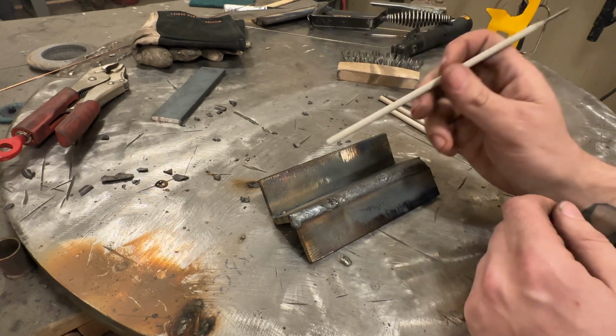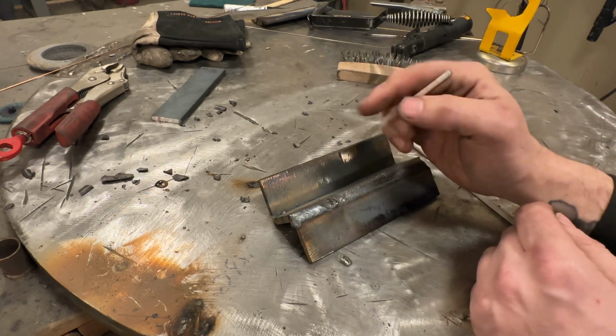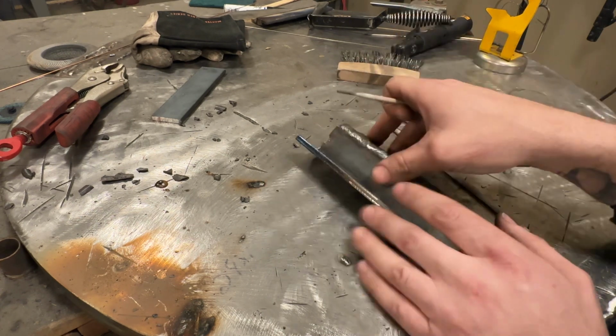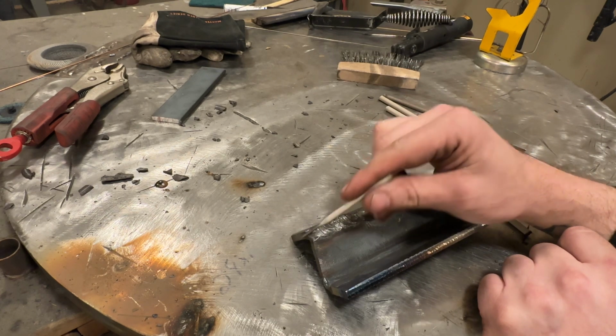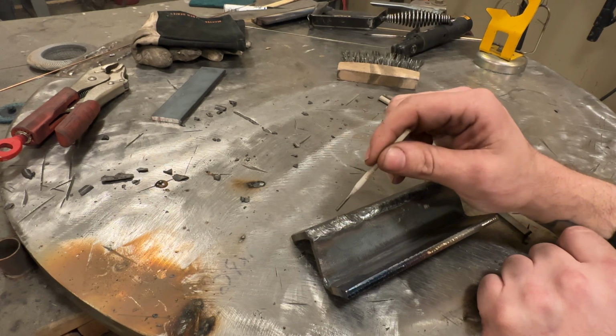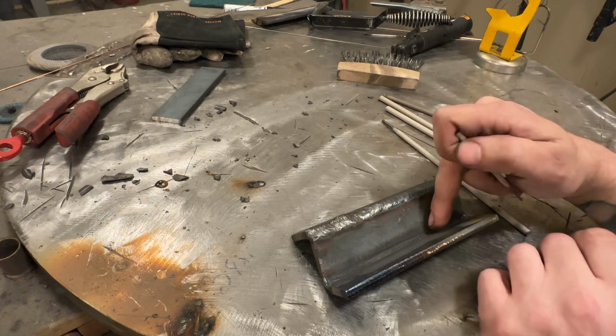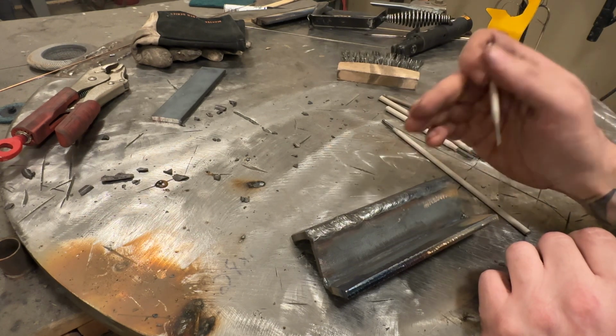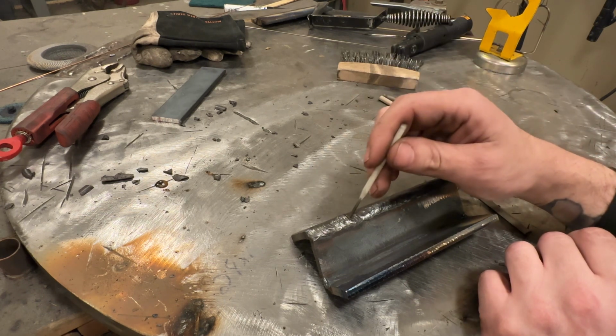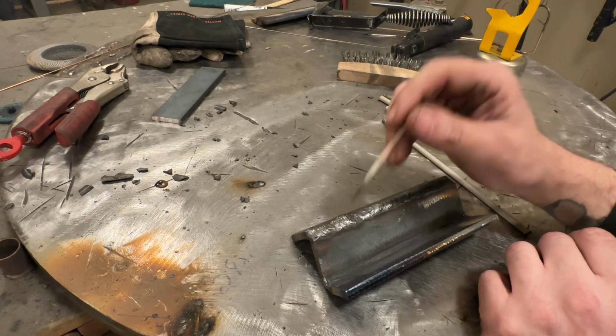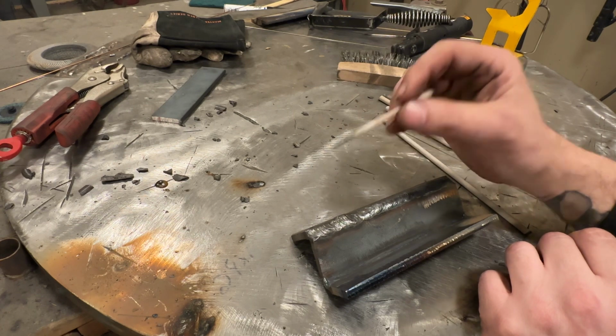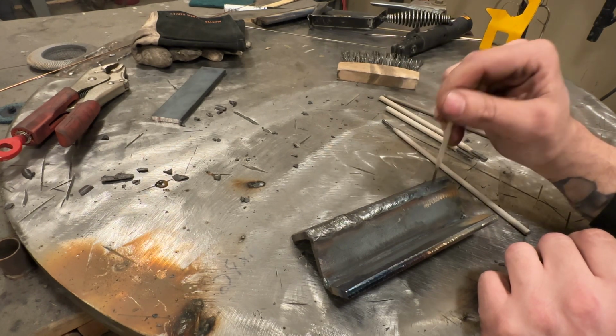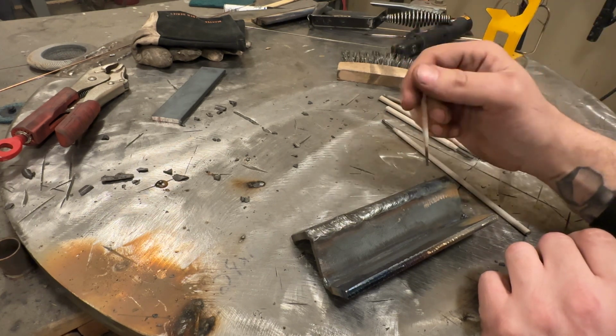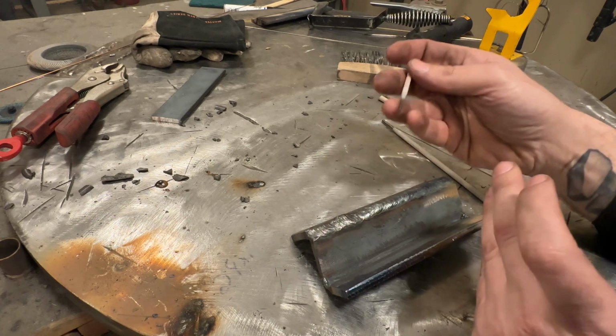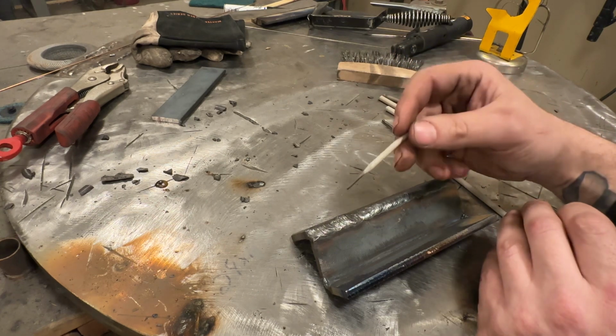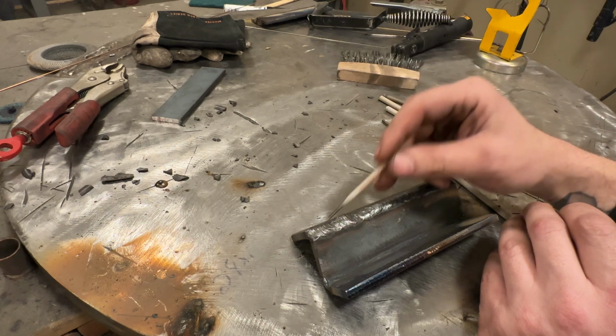And that has to do with why you don't generally want to take 3/32 rods like this little guy and sit there like you saw me do on this one right here, and just sit there pouring it in there, cramming it in there, because this will produce a weaker weld than this is. Now, is it weaker than this steel? Odds are no. But again, this is information, bits of cheese to chew off, to think of, is that anytime you take a small rod and just keep pouring it in there, it will produce a poorer grain structure, and it will produce weaker results than a rod run straight in with minimal feeding of it in, excessive feeding we'll call it. So what does that really mean? Well, it means that you should think about that next time you want to weld thicker plate, that maybe you should be using a more appropriate size rod for what you're welding.